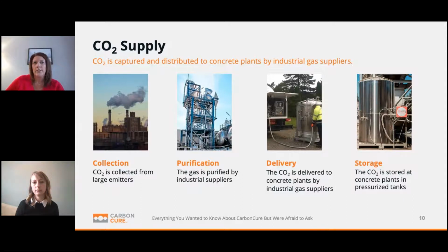So getting back to how it works, the CO2 supplier will permanently install a tank at any concrete facility where our CarbonCure technology is installed. As you see here, the tank is about 4 by 8 feet, and it's pressurized. Under pressure in that tank, the CO2 exists as a liquid. The CO2 supplier will come by the plant on a regular basis, typically monthly depending on your production volume, and they will just refill that tank with liquid CO2, and that's what gets used in the concrete.